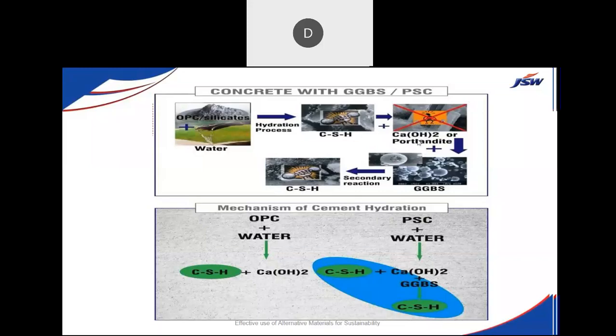So what will GGBS do? The moment you get these two products, the GGBS will immediately attack the calcium hydroxide and convert it into calcium silicate hydrate gel. This is what the pictorial diagram shows, that by using GGBS, definitely you're going to have a double reaction. So definitely double reaction means double strength.